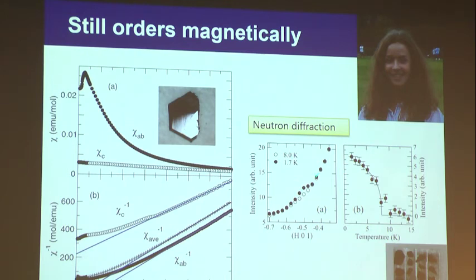So we actually did neutron scattering work on this material. Unfortunately, these crystals are all very small, so we had to make a large array of these crystals to do this kind of neutron scattering work. But in the end, we showed that there is magnetic order in this system. The ordering temperature is about 7 Kelvin, and the ordering is, again, zigzag ordering.